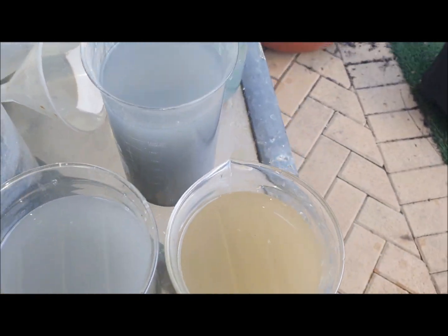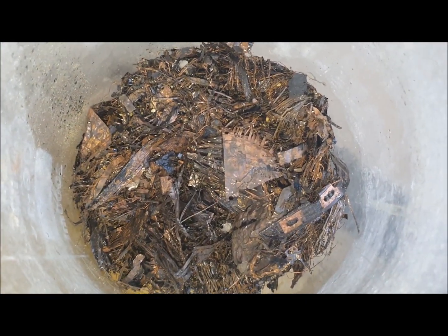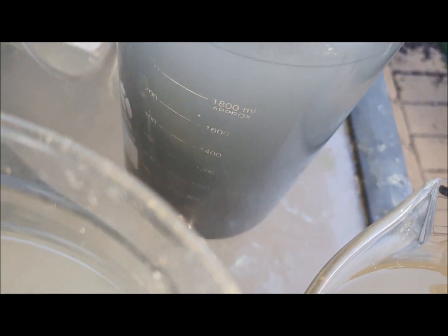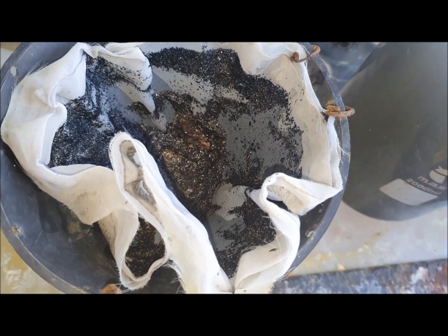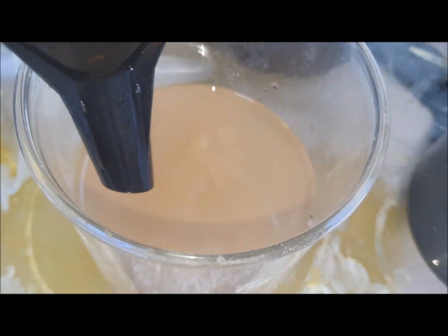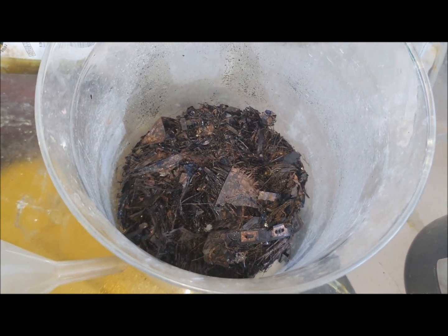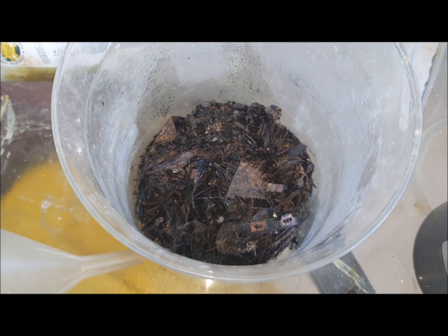I've rinsed the liquid off — I've rinsed about six beakers. You can see a lot of copper in there, but I waited until the liquid was coming out fairly clear — still a bit yellowish, but better than the grey it was before. I'll keep rinsing it, probably give it two more rinses, and then I'm fairly certain there's no tin left in there. I don't know what these colours are, probably small fragments of copper. Once I put all that back in, wash it a few more times, I'll put a nitric bath on — and just to make sure I got all the hydrochloric acid out, I'll give it a Stannous test in case any aqua regia formed and there's some gold in solution, but I don't think there will be.